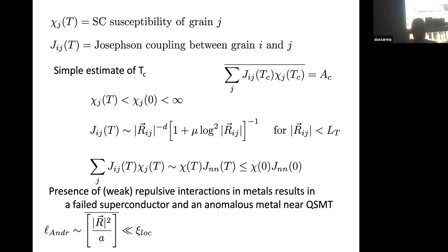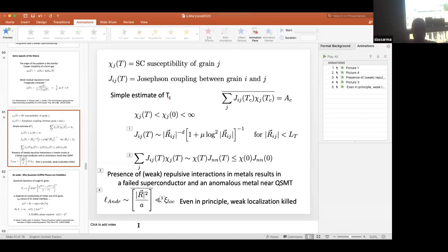But then I'm missing something. Then why wouldn't the system going ferromagnetic destroy it? I mean, you do not have S-wave ferromagnetic superconductors, right? If these systems were ferromagnetic, yes, it would be a problem, but they're not. Ah, I see. Okay. These are weakly interacting systems, and for the most part conventional singlet superconductors. So the fact that they remain metallic is the real mystery here, that the transition is between a metal and a superconductor, and that the metal is anomalous. It's got strong temperature and magnetic field dependences that a Drude metal doesn't.